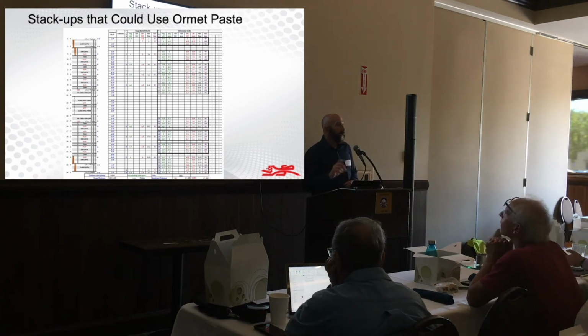So really, I like to see something in the order of 8, 10 mils. That doesn't mean you have to use 8 or 10 mil dielectric. You can still do that in a 4 mil dielectric. It's just a whole lot easier to apply the paste, less can go wrong. But you don't want to exceed 1:1.